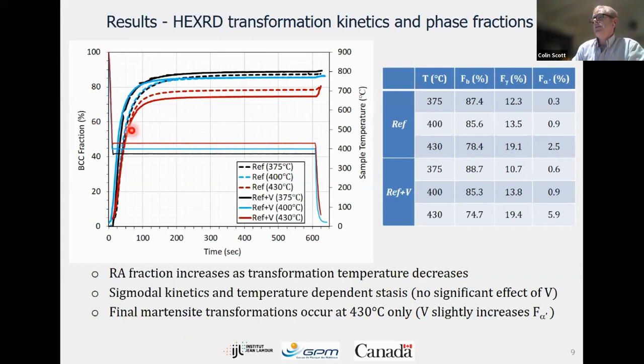Here are the thermal cycles. So the black is at 375, which is just above Ms in this case. The blue is at 400 and the red is at 430. And this is the body-centered cubic fraction, the bainitic ferrite fraction, if you like. So you can see quite clearly that the amount of bainite will increase as the transformation temperature decreases.